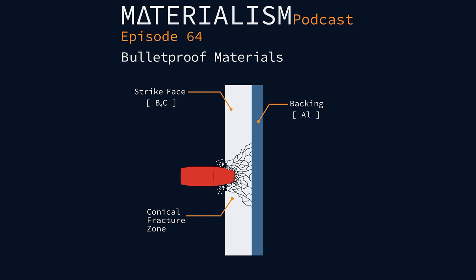Well, if you want to stop a bullet, we need something hard. And what's harder than ceramics? Ceramics are very much known for having very high hardness, very high compressive strength, which is exactly what you're dealing with. And so they make a lot of sense. If you're going to go with ceramics, you might as well go for the ones that can A, be manufactured incredibly well with as few flaws as possible, and your hardest materials that you're going to be able to manufacture consistently. So alumina, silicon carbide, boron carbide, titanium diboride, and then various versions of those with dopants.